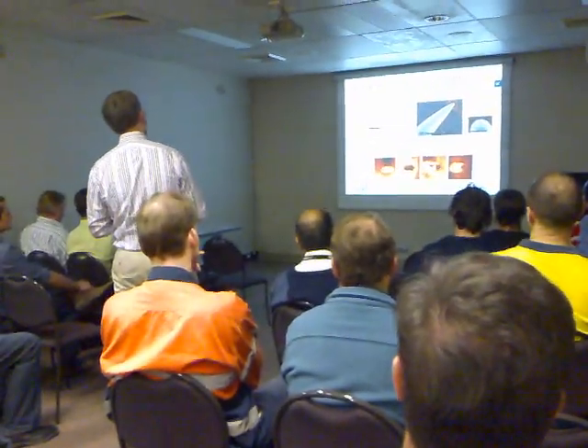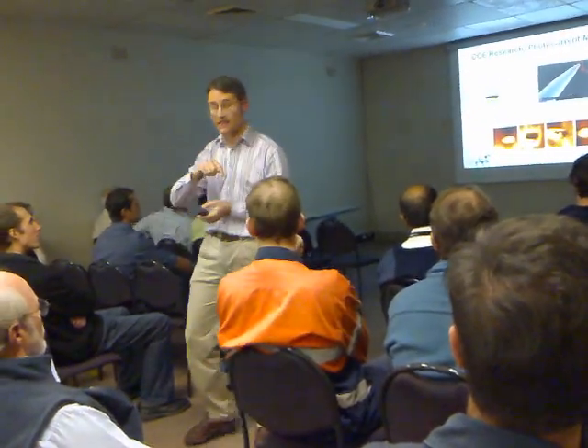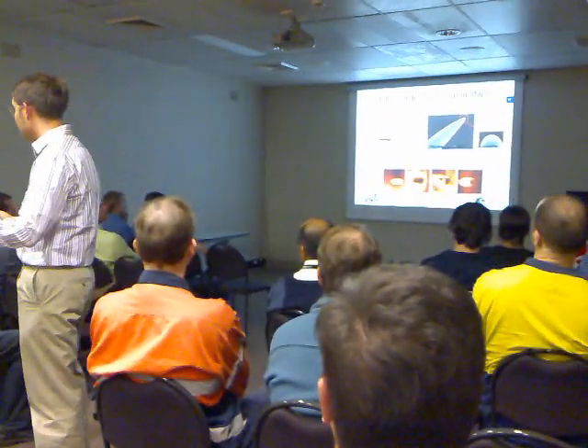This means we can measure the topology at the same time as we shine light down through the device. Normally one uses this machine to look at the light scattered from the surface — you're in the near-field and get really interesting absorption effects. We said: we can use this machine differently. We make a really thin metal contact on the top, build our solar cells, and measure the current that comes out as we shine that light through. For the first time, being able to map structure and photocurrent simultaneously. What people were doing in the past was saying, 'I've got a good solar cell and it's really rough, therefore rough solar cells must be good.' Then someone else would say their good cell is really smooth, therefore smooth must be good. That's just rubbish. What we wanted was a technique that would actually measure where the current comes from in these phase-segregated films.